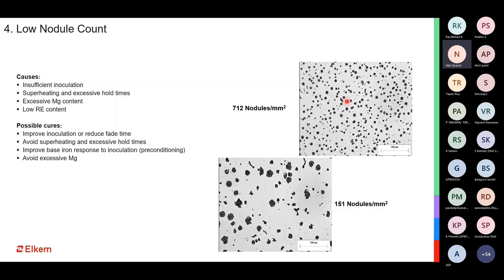So, starting with the first and foremost, if we have a poor nodule count in the system. Poor nodule count means, if you look at the photograph here, you can see a much higher nodule count. If you look at the photograph here, you see very few, bigger nodules. These are the same two sections, but they have a big difference in the number of nodules in the system. What are the causes? First and foremost, when you have insufficient inoculation, you do not create enough nucleating sites for the graphite to precipitate out.